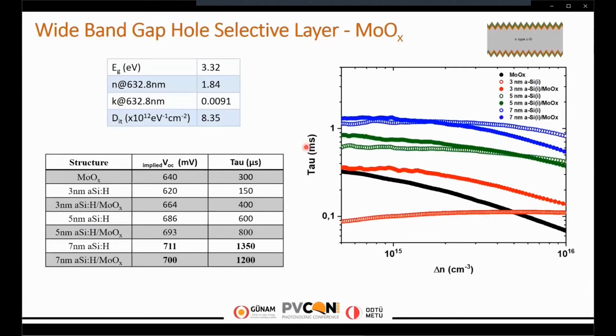We have checked molybdenum oxide passivation quality with various thicknesses of amorphous silicon layer. Starting from 3 nanometer up to 7 nanometer, molybdenum oxide enhances passivation quality. But when you look at the passivation quality of the 7 nanometer amorphous silicon, when we add molybdenum oxide on top of it, the passivation quality decreases. As you can see, implied VOC value decreases from 710 millivolt to 700 millivolt.